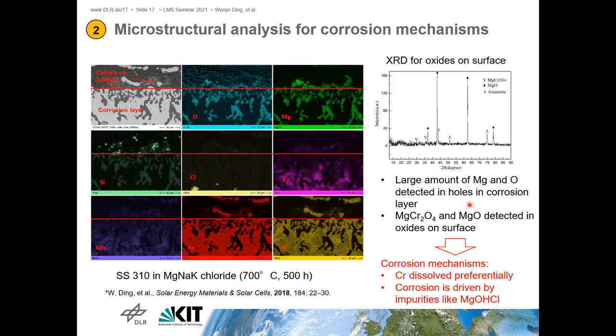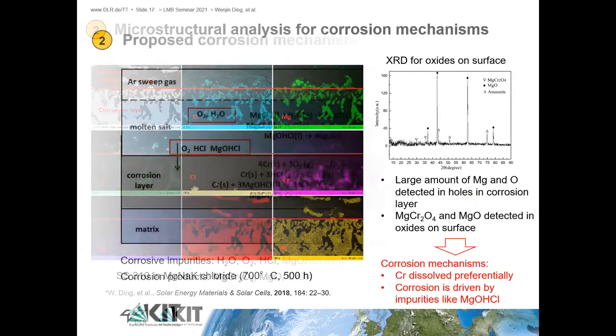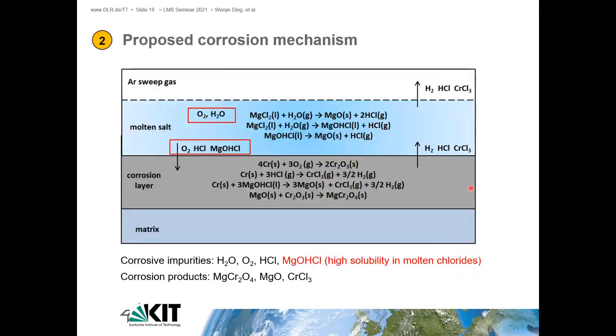Sometimes they contain some very strongly hygroscopic salt like aluminum chloride or magnesium chloride. So it will also absorb some water inside, and when it heats up to the operating temperature of the battery, the corrosive impurity will be produced. So my suggestion is that we should pay attention to the corrosion of the salt in the batteries.